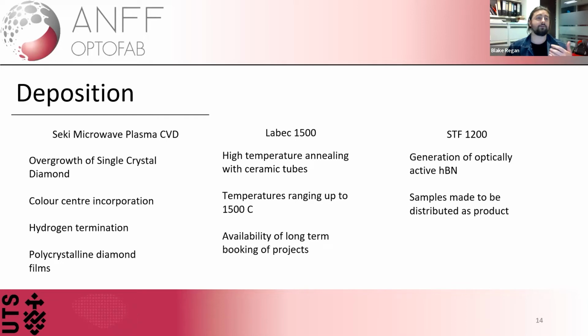So your diamond could go through a number of fabrication steps if you're doing anything else to it, which can create damage in a top layer of diamond. The CVD overgrowth process is proven to recover the diamond surface, and the new material does not translate any previous stress, strain, or roughness that's imparted on the previous layer, unless that roughness is so over the top that you'll grow polycrystalline just based on different facets. But in terms of things like, I know a lot of groups do work such as ion implantation, this can recover that damage quite easily.